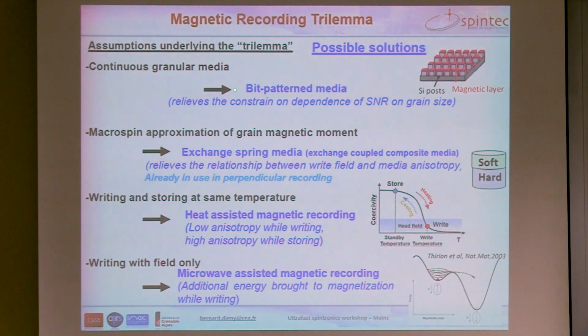One way is actually to no longer use continuous granular media, but move to bit patterned media. In bit patterned media, the material, the media itself, is nanostructured in the form of arrays of dots, and each dot carries one bit of information. So now you see that the separation between bits is defined by how we prepared these arrays of dots. And we no longer need to have 10 grains per bit here. We can have 1 grain. Each dot can be a single grain.